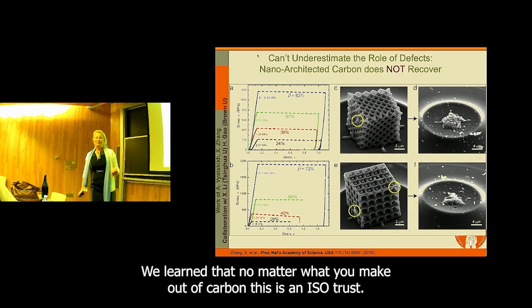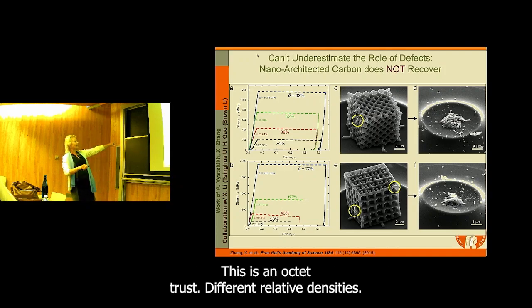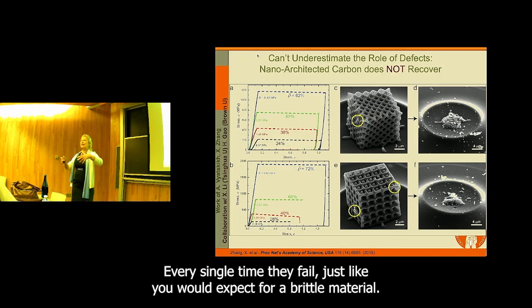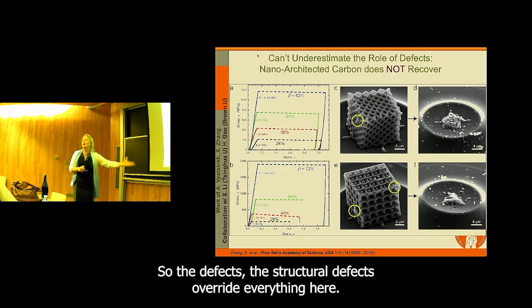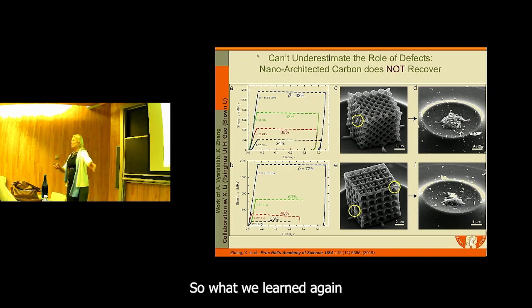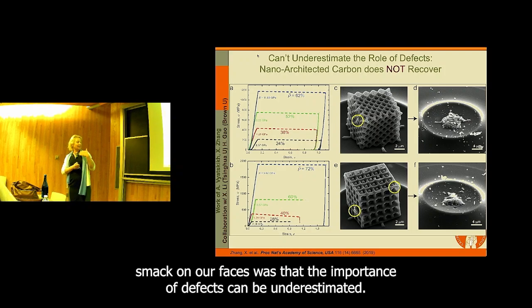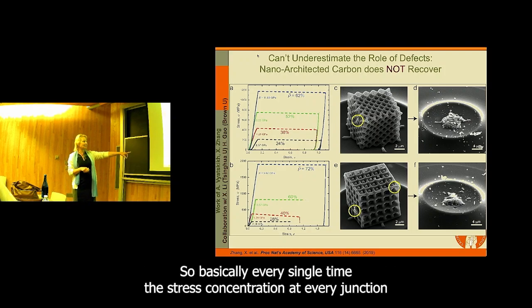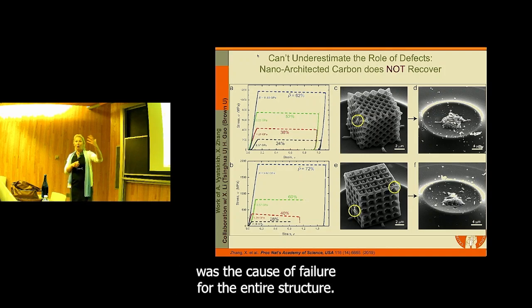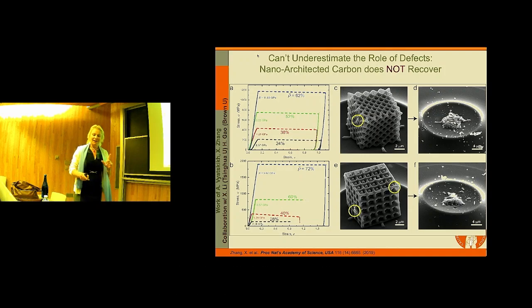Bad news happened. We learned that no matter what you make out of carbon, this is an octet truss, this is an octet truss, different relative densities. Every single time they fail, just like you would expect for a brittle material. So the defects, the structural defects, override everything here. So what we learned, again, smacked on our faces, was that the importance of defects can be underestimated. So basically, every single time, the stress concentration at every junction was the cause of failure for the entire structure.